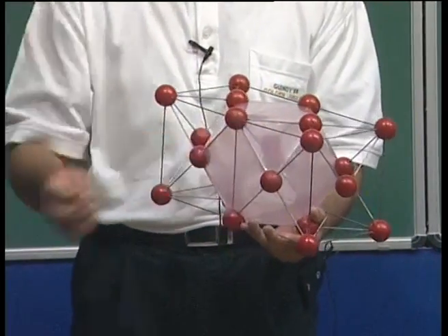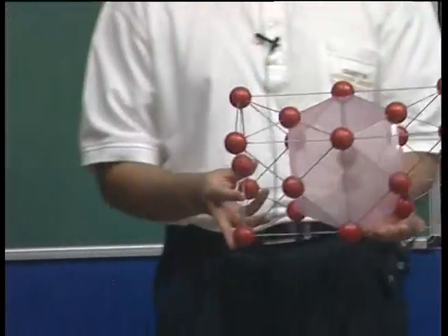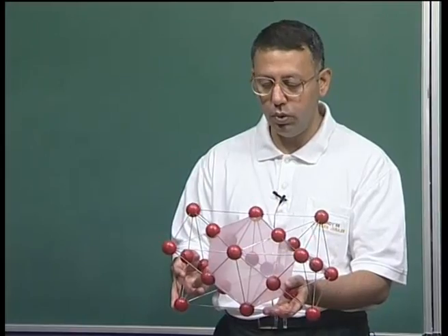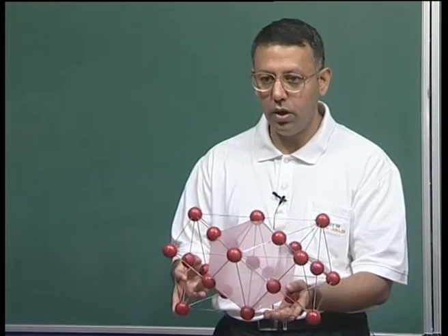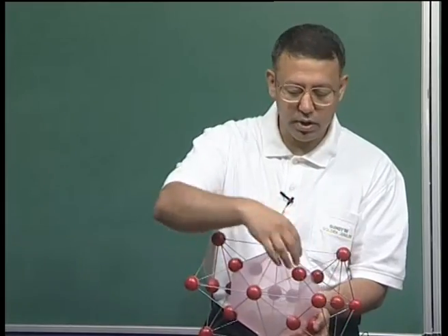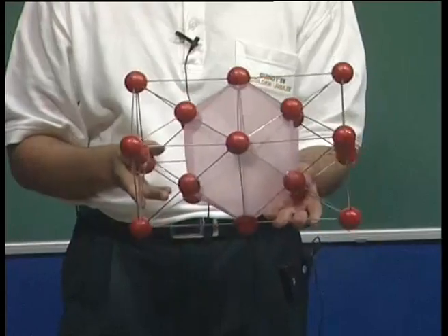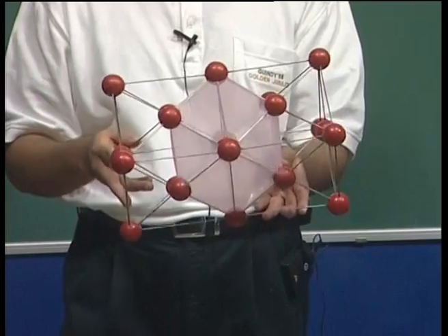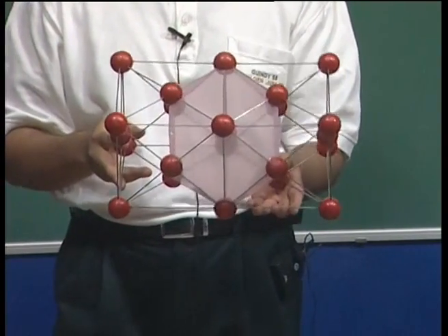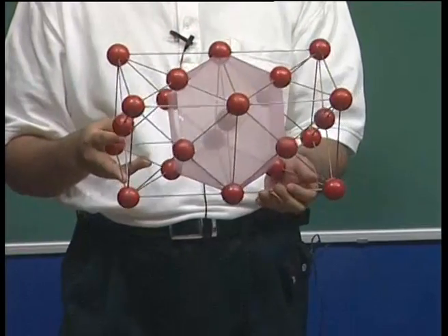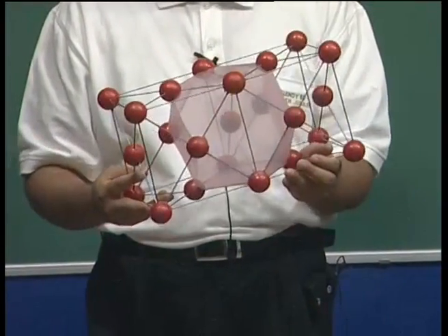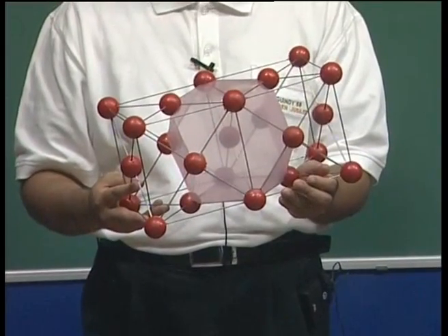As I can see, this will be the seat of the 4-fold axis, and this will be the seat of the 3-fold axis. Now even though I have chosen, as I said, the central atom here, the atom between the 2 unit cells, to be the center of the cube-octahedron, I can choose any atom in this cubic close-packed structure, and the coordination polyhedron I would obtain would be a cube-octahedron. Another point to be noted here, which we shall see in some other solids is violated, is that every atom is exactly located at the same distance from the central atom, which is root 2 a by 2.